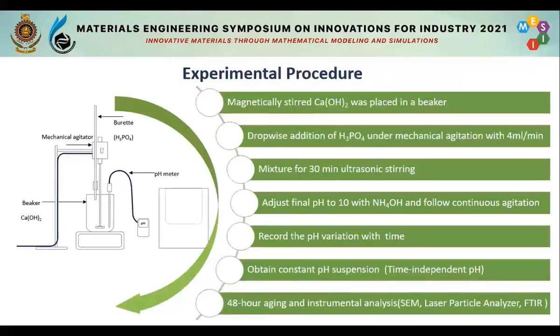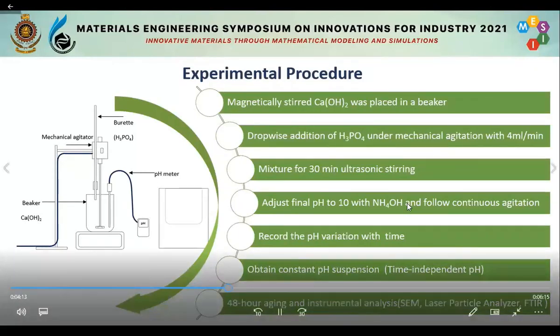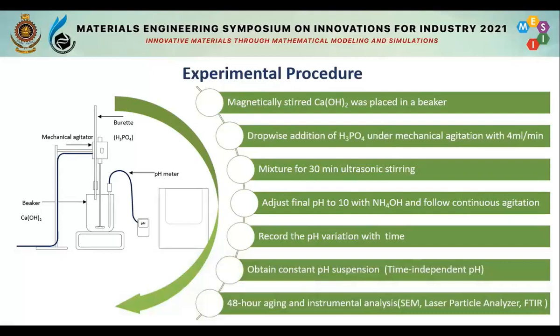In the experimental procedure, we did some magnetic stirring of the calcium hydroxide solution. Then we added orthophosphoric acid dropwise with our mechanical agitation setup. Then we mixed our solution for 30 minutes with ultrasonication. We adjusted the final pH to 10 with ammonium hydroxide, and then we recorded the pH variation. Most importantly, we finally obtained a constant pH suspension. After 48-hour aging, we did the instrumentation analysis for our samples.